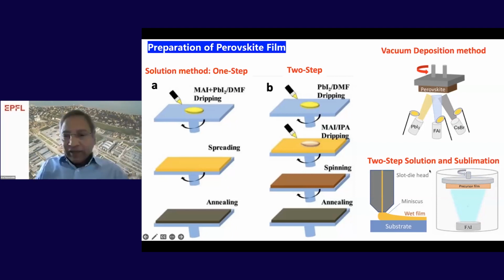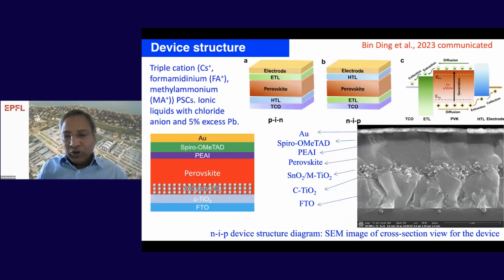However, the other technique is a two-step method with slot die coating, because these are the techniques for small devices. For large-scale applications, slot die coating is a very important technique, where you first deposit lead iodide by slot die coating, and then you expose it to methyl ammonium iodide or formamidinium iodide, the organic cation, to form the perovskites. So this two-step solution followed by sublimation technique seems to be more suitable for industrial applications. So that's it, preparation of the perovskite films.